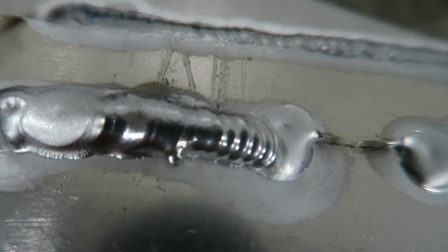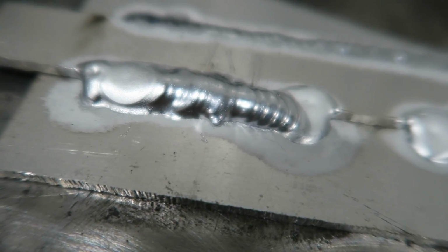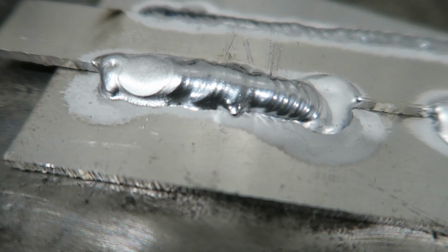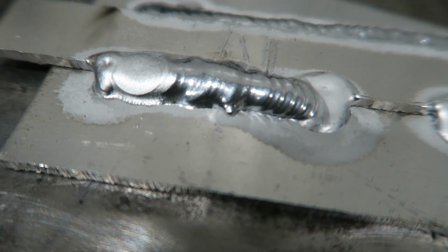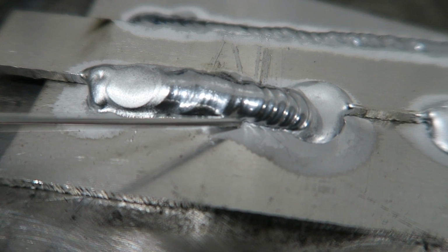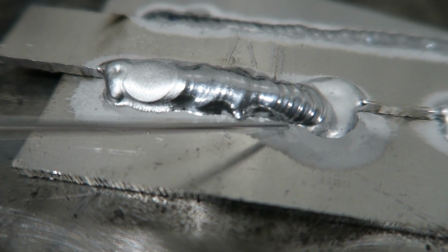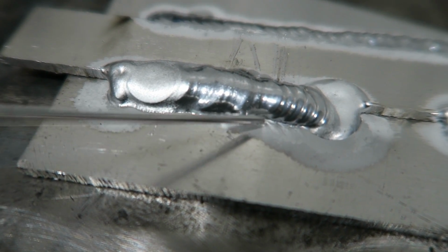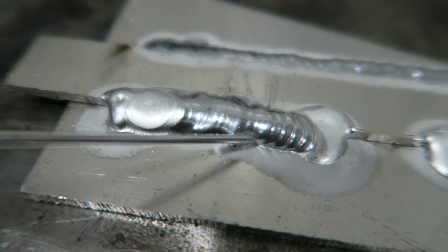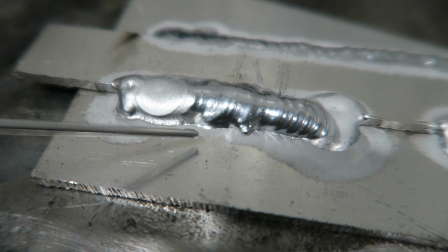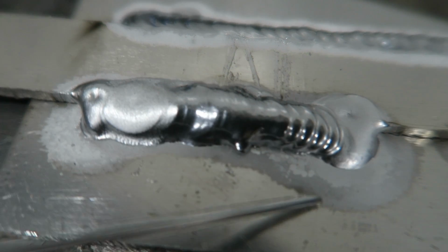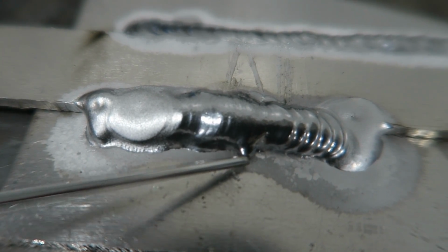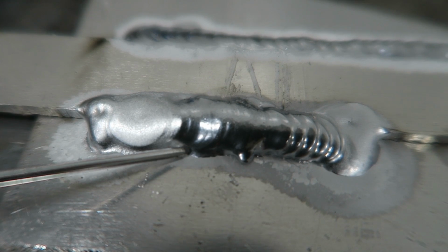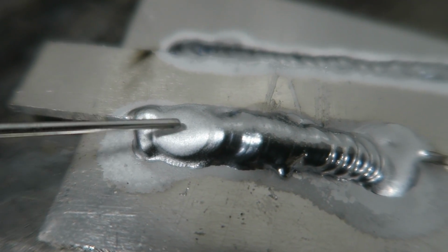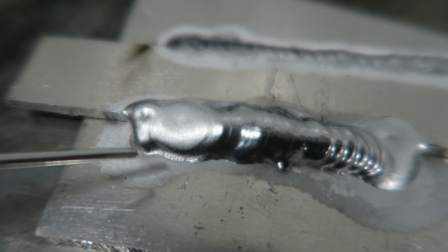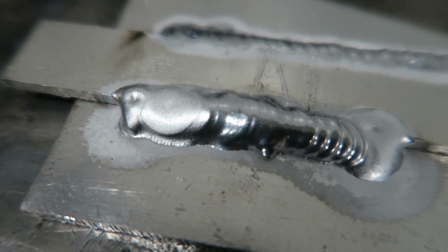Here, less amperage, too little. You can see that there is a space. Let me see if I can get something better to point with. There we go. There's a space right here where there's no weld metal, and the weld metal sucked back beyond itself. We didn't have enough heat here to actually burn into this metal, and you can see evidence of that with the cleaning action. Here's your cleaning action right here. You see that you lose it almost completely by right here, and then we added too much heat in here and ended up with more washed out puddle.